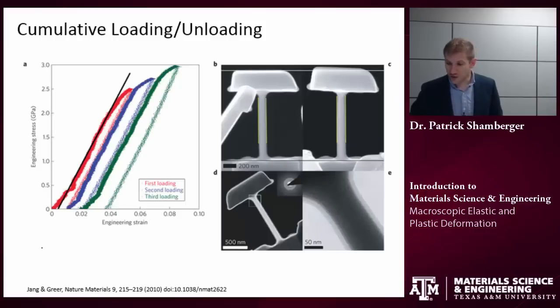And we see this in real data. So this is an example from a nanopillar, I believe it might have been a metallic glass. But what you can see is that we have very linear behavior initially. The yield stress is somewhere up here for this material. Once we go past that, we have some plastic deformation. But it still recovers elastically. And so you see that these slopes exactly mirror that initial slope. So this is the elastic recovery. So, for example, in this red curve, the plastic deformation would be this distance. And the elastic recovery, in this case, is much larger.